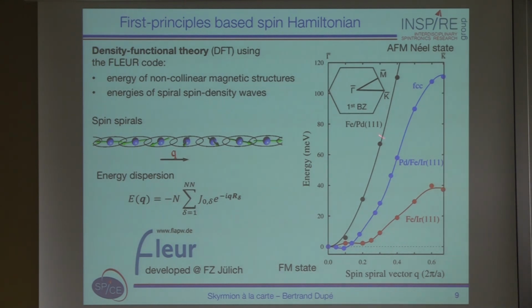And you see first, if you look at the iron on palladium 111, the energy is 0 at the ferromagnetic state, which corresponds to q equal to 0, and is maximum in this state, which is the antiferromagnetic Néel state, which is so high in energy that we don't put it on this graph. It means that this antiferromagnetic state is unstable and the ground state here is ferromagnetic. If you go on the other side of the spectrum, you take iron on iridium 111. And here the situation is different.